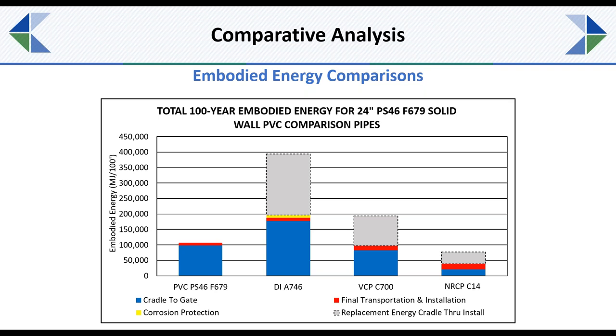And similarly for the NRCP, the non-reinforced concrete pipe, they actually have a much lower lifespan, mainly due to the fact that in sanitary sewer applications, that concrete will be corroded by these sewer gases there. For ductile iron pipe, again, they looked at overall 100-year lifespan with the replacement cost, as well as removing the replacement cost to see how that works out. So PVC pipe does perform fairly well with the embodied energy for the large diameter sanitary sewer.